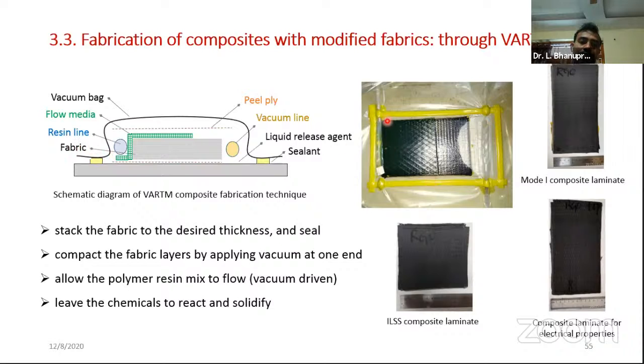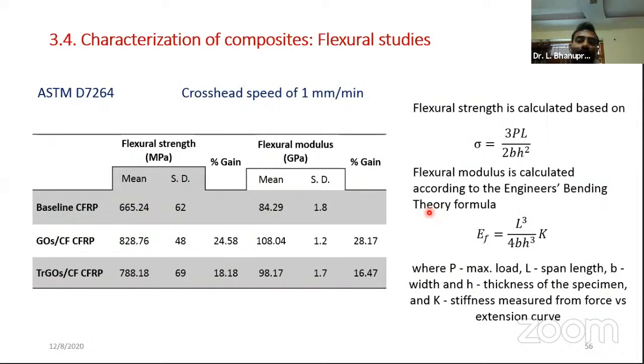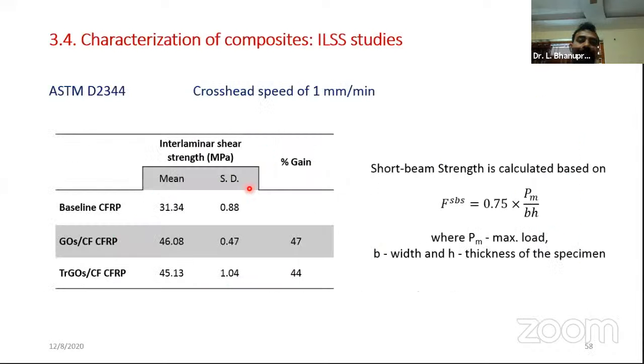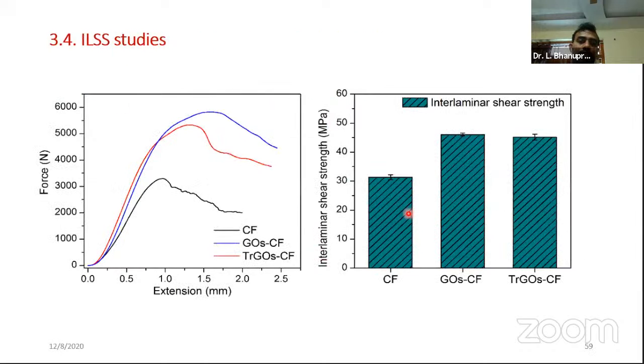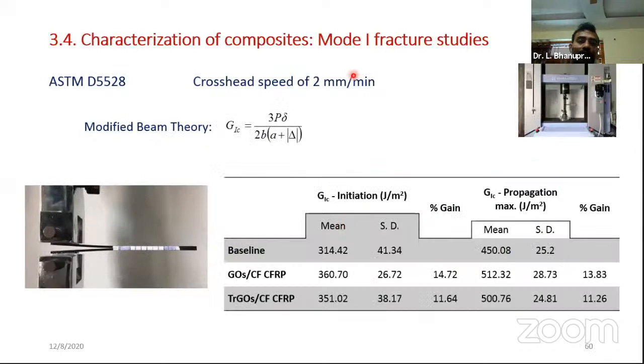So resin is driven from one end to the other end point, and we have tested the flexural strength. We have noticed a very good improvement of 25%, and we tested the ILSS, interlaminar shear strength. ILSS has been significantly improved, up to 45%. Mode-one fracture we have also done, and that increased by 15%.